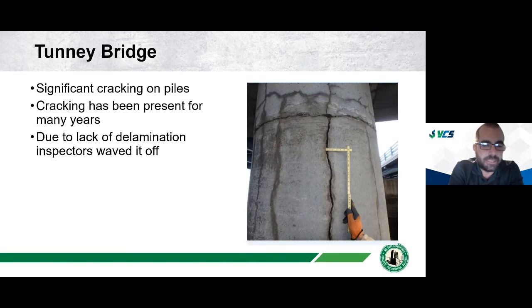It's kind of interesting, as most people would know, every 2 years you have to go out and do a bridge inspection, and this is done. The engineering firm that held the contract to inspect the New Jersey bridges in this area had been doing their 2-year inspection for years, and they observed these cracks on the piles, but there was no associated delamination with these cracks. And typical bridge inspectors, first you see cracks, then you see delaminations, then you see spalls. That's the progression they're expecting.